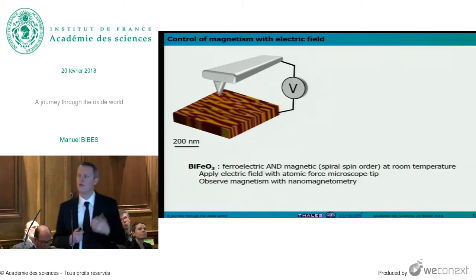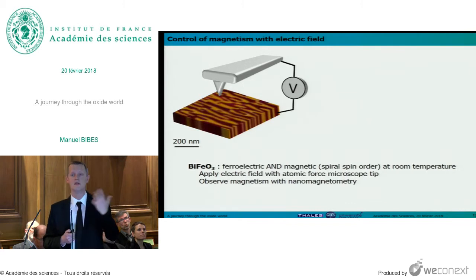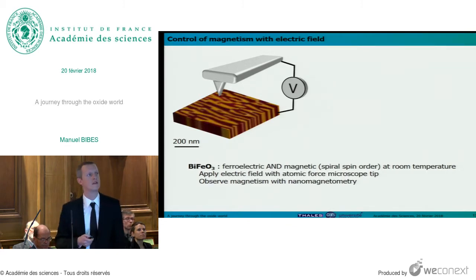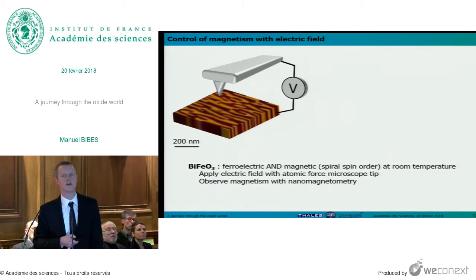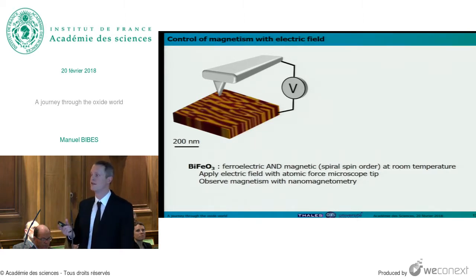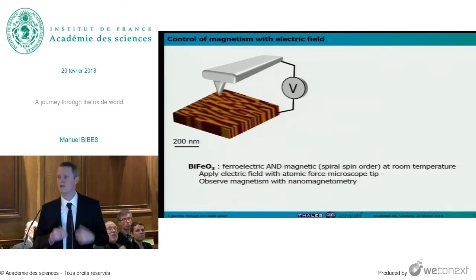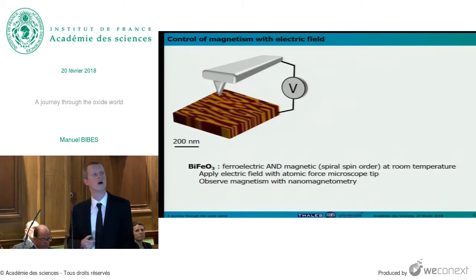Now I want to give you a few examples of some experiments that we have done in our lab in different perovskites that we grow by the same technique. The first one is with this material which we call bismuth ferrite. It has oxygen 3, of course, and then bismuth and iron. It is a material that is at the same time ferroelectric, so it has these ordered dipoles, as I showed you, and at the same time it is magnetic. This is very rare, to have this coexistence, and we call these materials